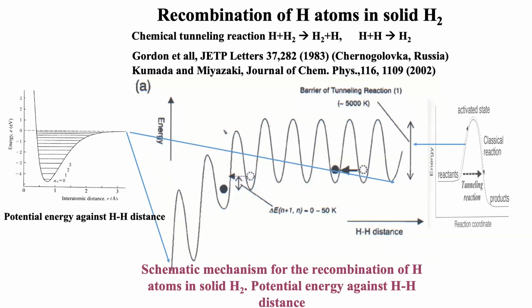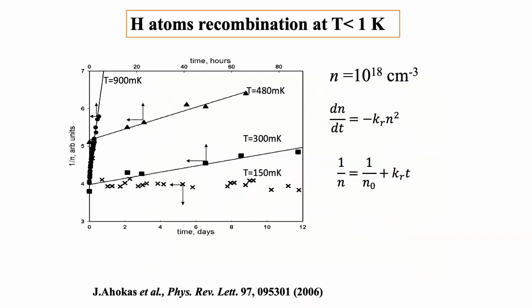When this atom and that atom are very far from each other, the tunneling is resonant. But when the atoms become closer and closer, there's a mismatch between the levels in the closest lattice sites, meaning tunneling should be slower. So at low temperature, the tunneling should be slower.